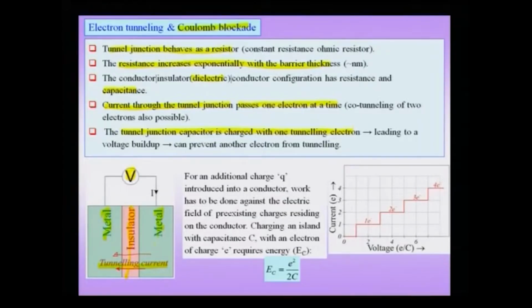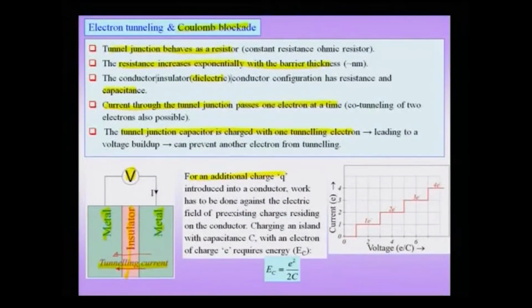Once this tunnel barrier has been charged with one tunneling electron, if I want to push the second electron through this system across this voltage, the first electron has already built up a charge because of the capacitance of this insulating layer. Work has to be done by the external voltage to push the second electron. That implies for an additional charge q to be introduced into the conductor, work has to be done against the electric field of the pre-existing charges residing in the insulating layer.